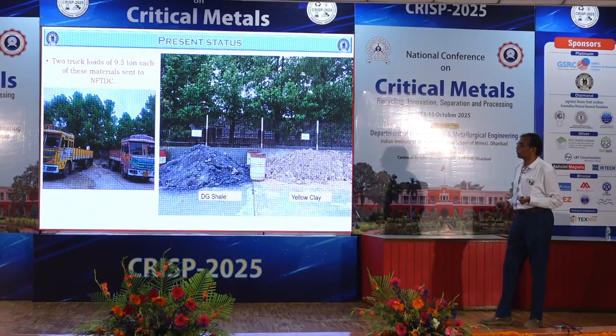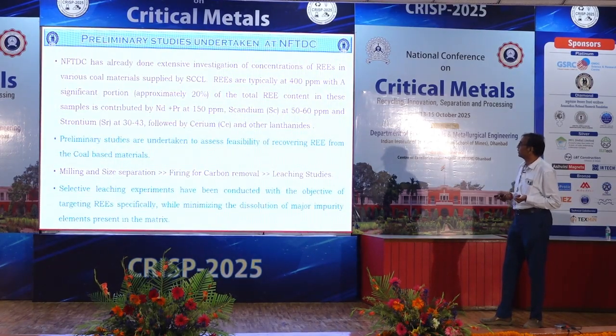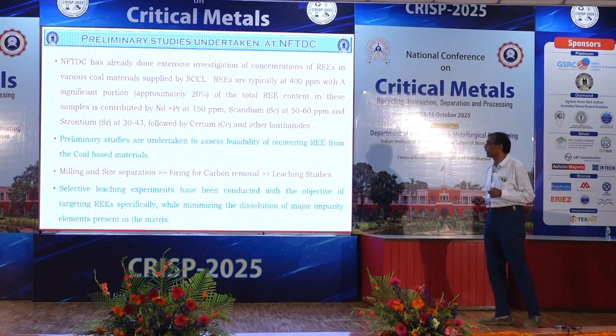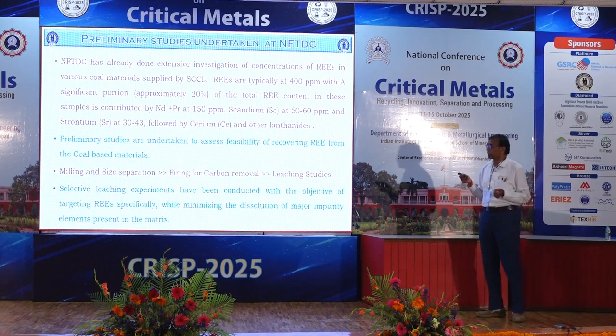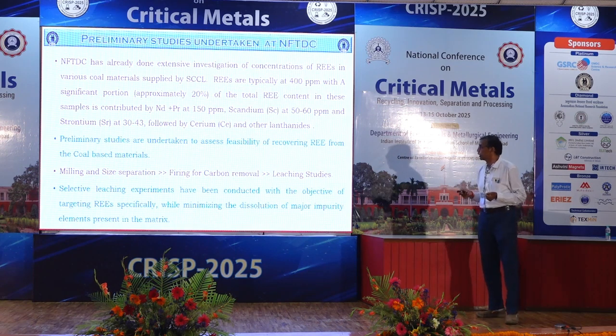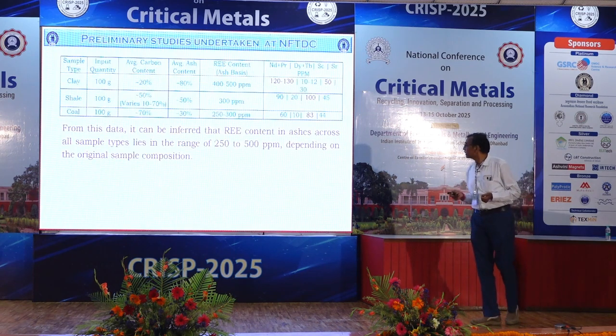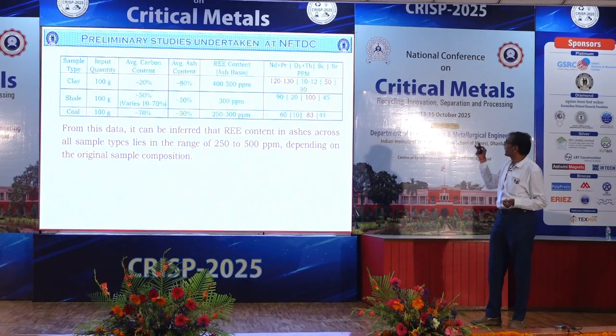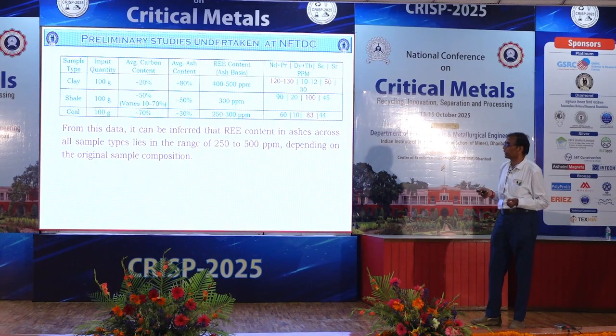So we sent them 2 truckloads instead of gram-scale samples. They conducted kg-based analysis and proved that all those elements are available there. Typically neodymium and praseodymium together 150, scandium and strontium, and dysprosium, terbium and holmium are also available there. So this is the main thing: clays have around 500 ppm, shales 300 to 400, coal only 250 to 300.